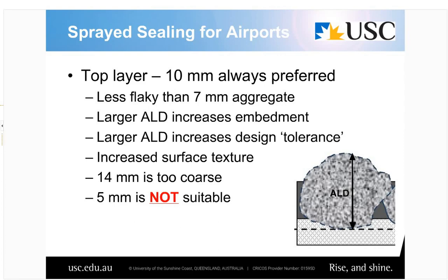Your tolerance that you're aiming for is actually less than the natural variability of the surface, making it essentially impossible to build a very small sized seal over a typically variable existing surface without getting too much bitumen in some spots and not enough bitumen in others.